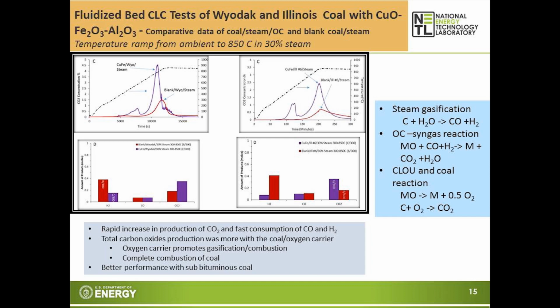These are the CO2 concentration data during the temperature ramp. For comparison, I also included the data with the coal and the steam without the oxygen carrier. These are the data for Wyodak coal, which is a sub-bituminous coal, and these are for the Illinois number 6 coal, which is a higher rank bituminous coal. As you can see, when the oxygen carrier is present, the CO2 production rate is significantly higher than that with the blank coal.